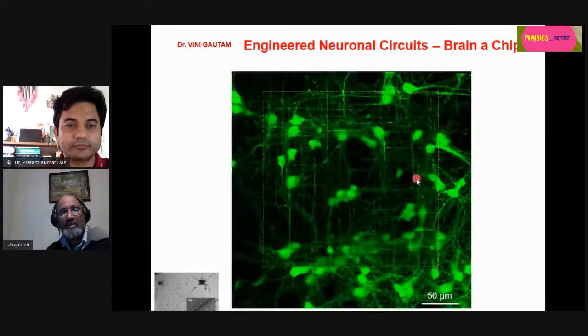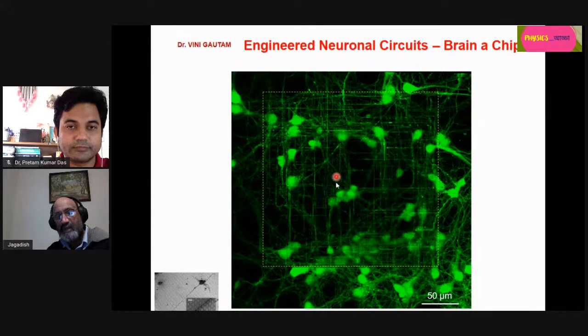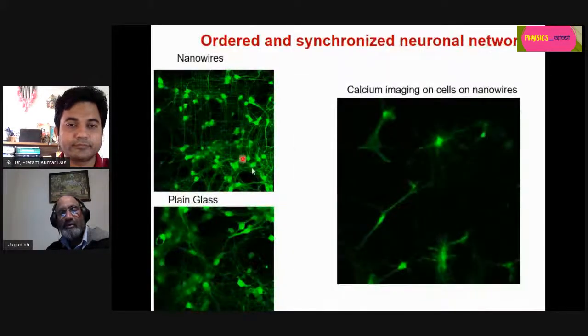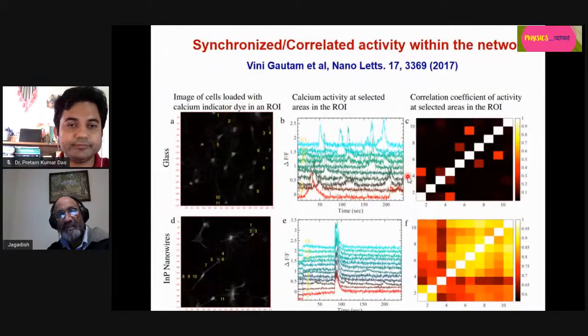We're able to show that if you grow more than one neuron, they form a nice network on these indium phosphide nanowires. And Vinny was able to show that these neurons are really communicating very effectively in an ordered and synchronized network, and we're able to correlate it. So this is really leading to exciting development.